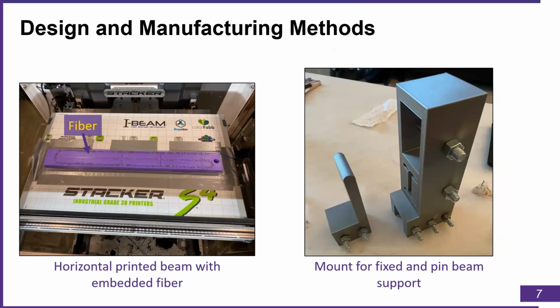The picture on the left is the horizontally printed beam. This is on the Stacker, and you can see where the fiber is. Essentially how we bonded this was we took some excess filament and we used a hot iron. So we laid the sensor in there and we basically just welded the sensor into the beam. So it was one solid piece and it wasn't going to move.